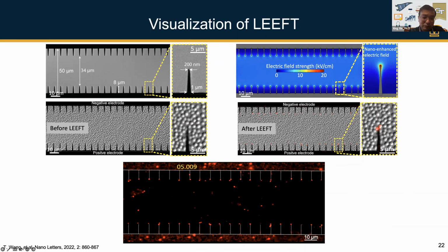So several pieces of information can be gained here. So first, this process is actually very fast, right? So you can see it's a few seconds. The effective treatment time is actually in the millisecond range. Because what we're doing here is not a DC voltage, it's actually electric pulses. So we turn on the voltage and then turn it off for a period of time and then on again. So it's electric pulses. So the effective treatment time is in the millisecond scale. So it's a very fast treatment process. And the second is that the treatment is really limited to certain ranges, right? So only in these places where we have a strong electric field will you see the inactivation by the LEEFT.